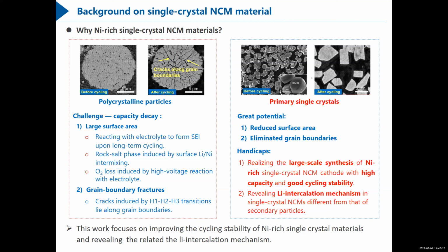On the other hand, single crystal materials have great potential because they have a reduced surface area. That means eliminating the grain boundaries, right? But there are also some problems with these materials. The first one is how to realize large-scale synthesis of nickel-rich single crystal materials. And what kind of lithium intercalation mechanism is in these materials? So this work focuses on improving the cycling stability of nickel-rich single crystal materials and revealing the related lithium intercalation mechanism.